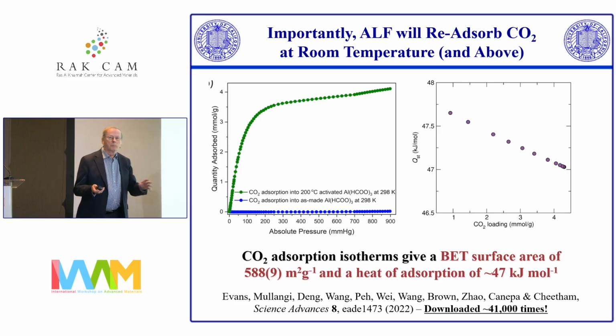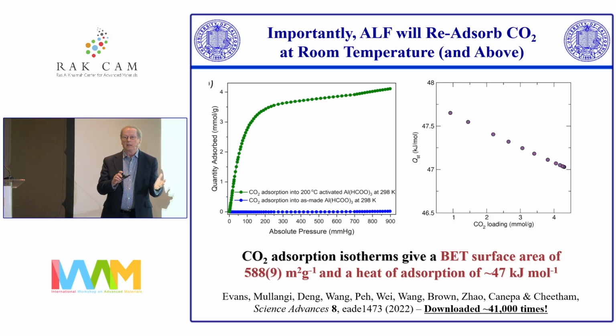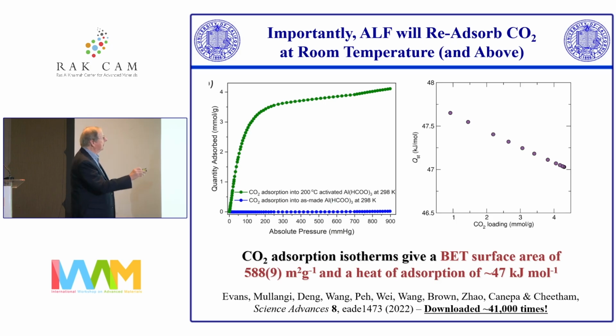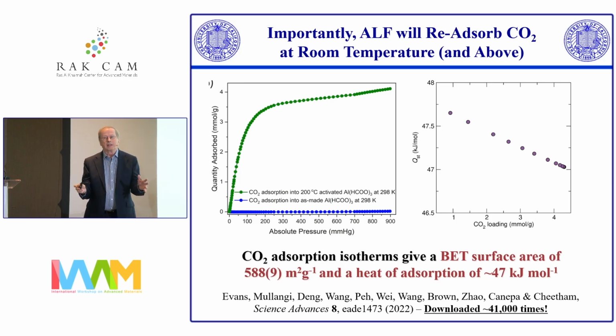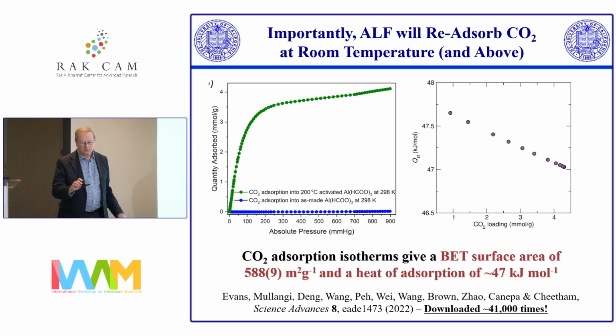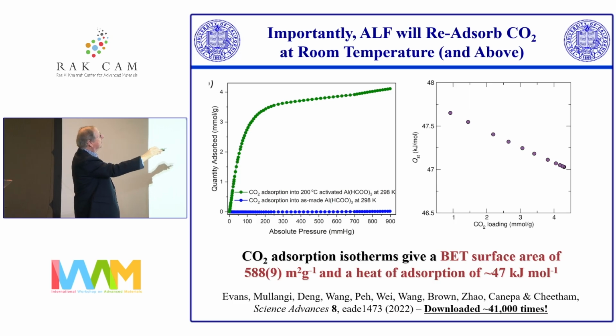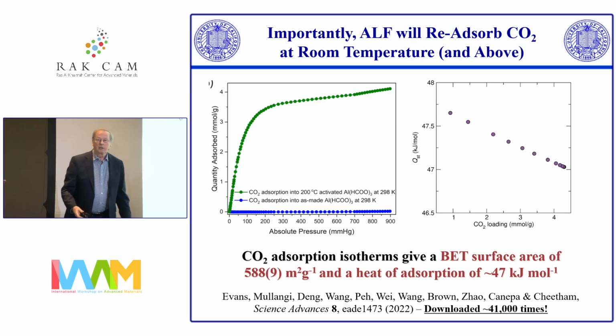We are able to show that it will re-adsorb CO2. And it gives you very respectable loadings of about 4 millimoles per gram here. And so this is the activated material. And of course, if you take a material that's not been activated, still got stuff in the cavities, it doesn't adsorb anything at all. And we have this here because we wanted to file a patent and demonstrate that this was genuinely new. And so the heat of adsorption is between 47 and 48 kilojoules per mole.